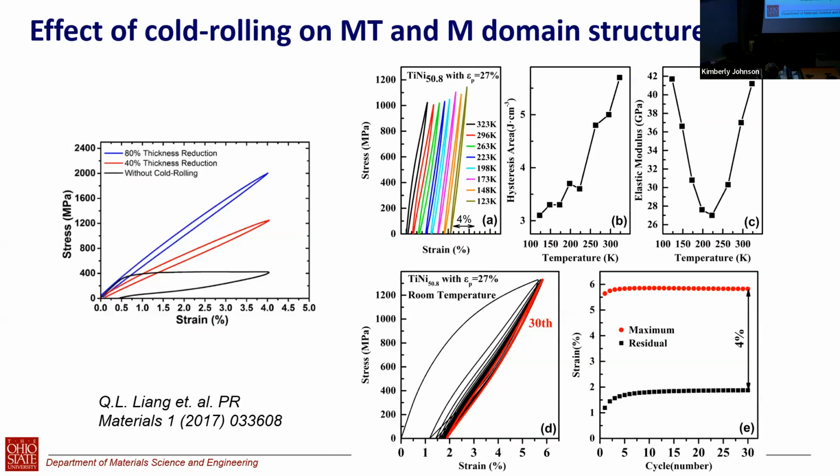All right, and then if you do the mechanical properties, you can see this is a linear superelastic. It's very easy to stabilize. This is, say, the first cycle, second, and then the 30 cycles, you have very stable linear superelastic. Usually, for shape memory alloys, you have to stabilize for 1,000 cycles. It's called the training process.